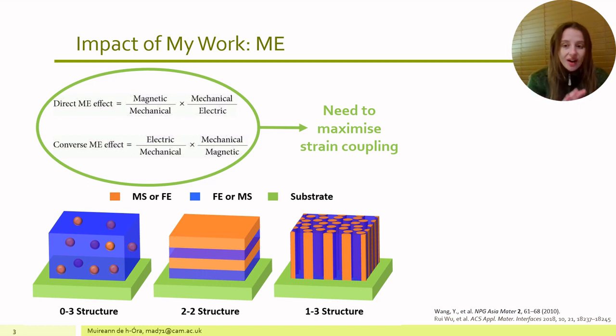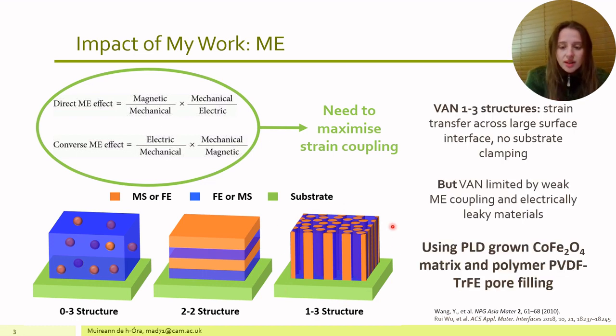So the impact of this work on magnetoelectrics, as we all know, in both the direct and the converse effect, the mechanical strain elements are so important and we need to maximize the strain coupling. If you look at the standard structures for magnetoelectrics, one of the main points is the strain transfer, and VAN or 1-3 structures allow this transfer across a large surface interface and there's no clamping from the substrate. But VANs have been limited by weak magnetoelectric coupling and electrically leaky materials by using only PLD compatible materials.